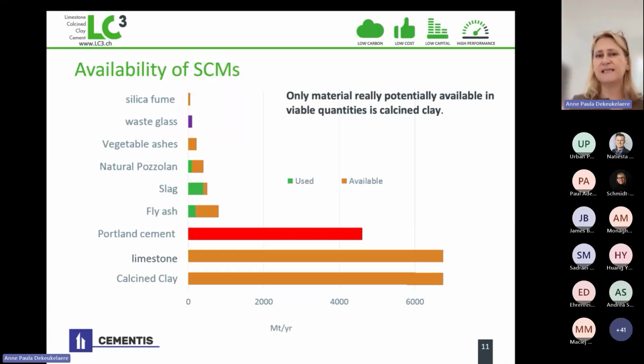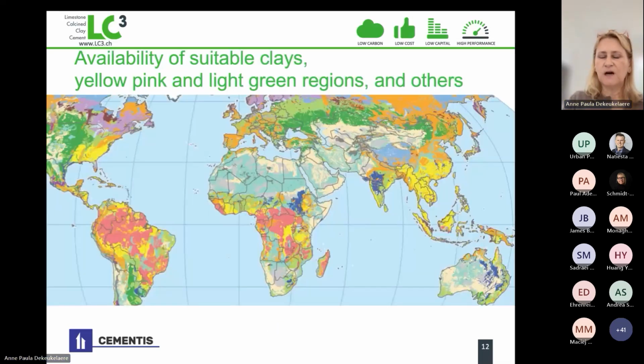Just to show the availability of SCM worldwide in terms of quantities, you see the slag is used nearly at 95% worldwide, and there is a certain quantity available. Fly ash is available, and we also use much, but there are a lot of different qualities in fly ash. Then you have Portland cement, that's a huge volume, and we have the two elements, limestone and calcined clay, that are extremely available worldwide. So availability is not the issue. Here you can see all the regions in yellow, pink, and light greens are where suitable clays are available. Suitable clays, we mean by that kaolinite content clay.